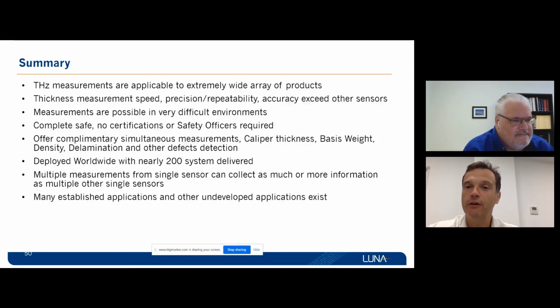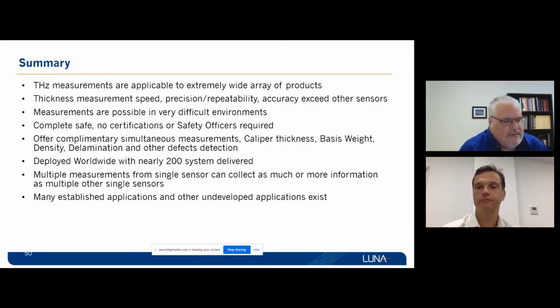Okay. So you'd also like to know, with your handheld sensors, how do you maintain a constant standoff distance from the object? Okay, so there's actually two ways. If you don't mind touching the object, then we put these little passive nose cones on, so you just simply put the sensor down onto the surface, and as soon as it touches the surface, it makes a measurement. Now, the height or thickness of that nose cone does not come into the calculation, actually. It's only there to aid the user to bring it to the right height.